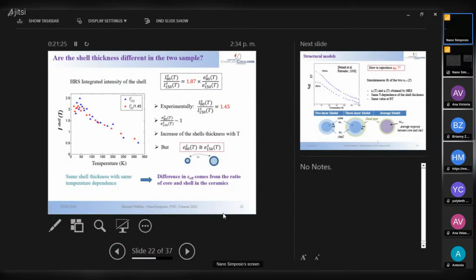And so, if you now plot as a function of temperature the intensity of the shell, you see that if you multiply the intensity of the shell of the small grain size ceramic by 1.5, you find exactly the same as for the large grain ceramics. I don't want to go into detail of this, it's really easy to understand, but this says that you have exactly the same temperature dependence in both ceramics of the shell size, shell thickness. So that means that the shell thickness in both ceramics is exactly the same. So the difference in effective permittivity just comes from the ratio of core and shell in the ceramics, not more than that.